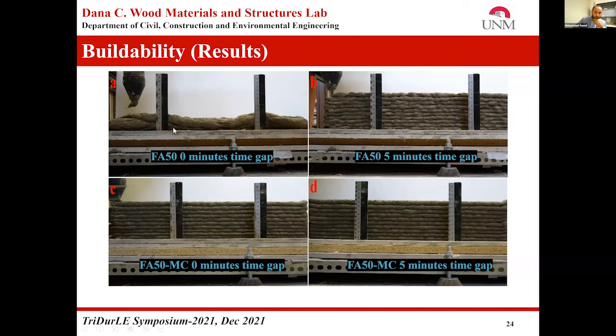So at 0 minute time gap, the standard ECC mix without any addition of admixtures will collapse after printing the 5 layers. And if we compare the same mix with the addition of MC, you can see the difference in printing quality, and the mix was buildable enough even at 0 minute time gap. But for the standard ECC mix the buildability was good at 5 minute time gap.